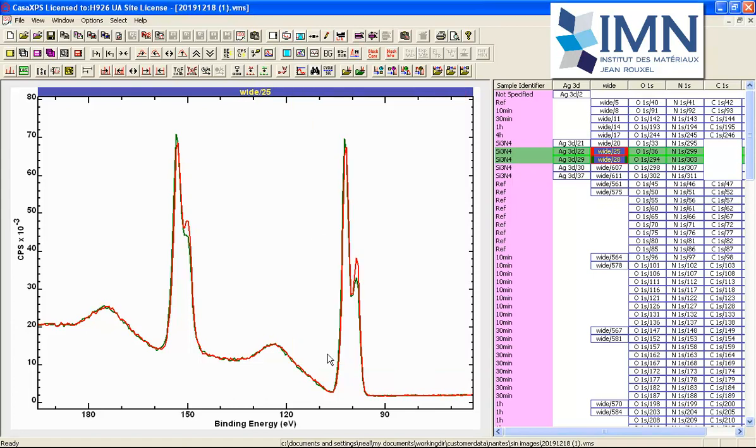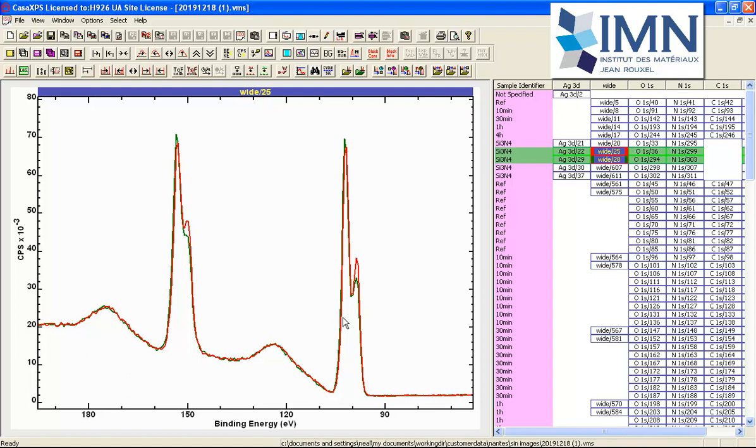While these peaks appear to be a single measurement, there are in fact two measurements. It is entirely feasible that the difference in these peak positions are due to an alteration in charge state with time. Two scans were measured separately and potentially we've got two different peaks for two different scans.